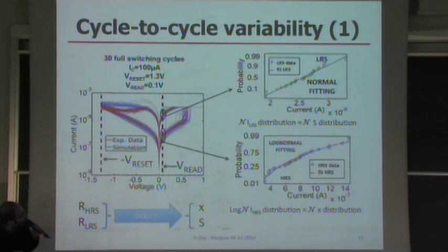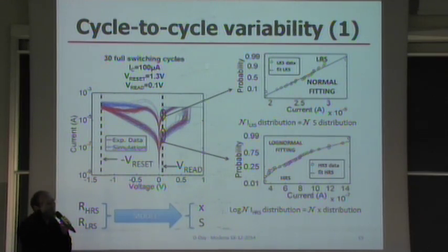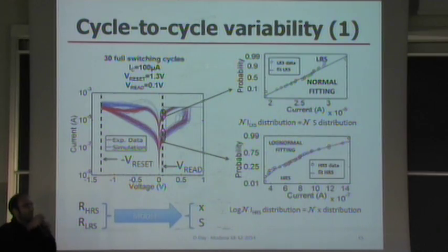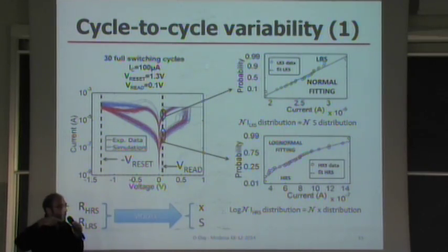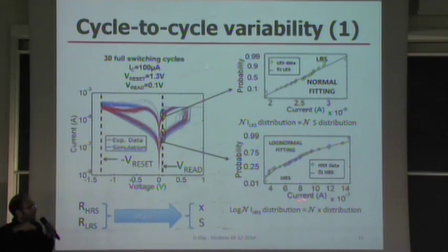But if we look at the current in HRS, then things are different. Here we clearly see not a normal behavior, but a log normal behavior. And a log normal behavior is related to a normal distribution of the barrier thickness. When we are in HRS, we have a dielectric barrier, and we have fluctuation over cycling of this barrier thickness just because of the intrinsic randomness of the reset process. It involves several atoms and ions. So we expect this distribution to be normal, and as a result, this reflects in a log normal distribution of the current just because the two are exponentially related. So if this varies normally, this is exponentially related to x and is gonna show a log normal distribution.